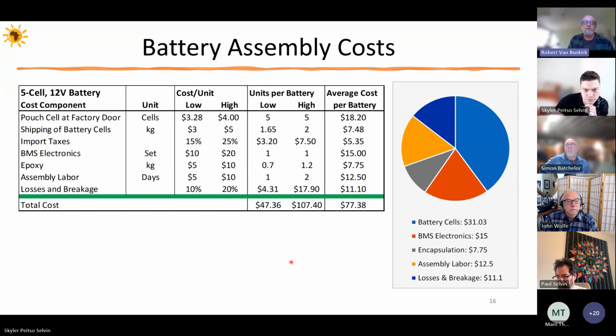So the total cost of doing a 5-cell battery is about $77, though, depending on how well we manage the costs of the different components, this can range from about $47 up to above $100. And that's roughly the cost we're working with. Maybe if we have higher capacity cells, the marginal cost of extra capacity isn't quite so big. But this corresponds to about 70 cents per watt hour. Next slide.